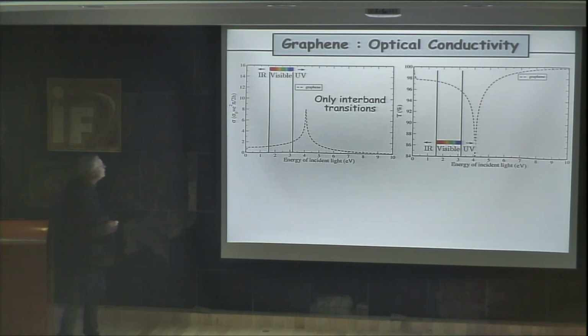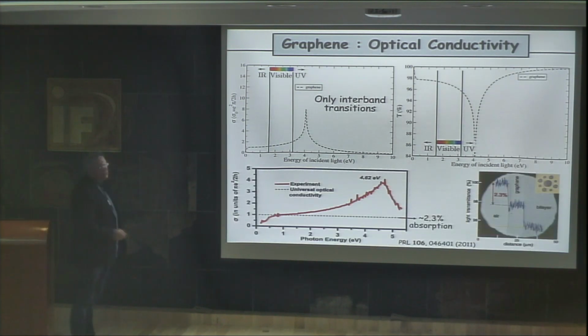So if we now want to calculate the optical conductivity, let's start with graphene to see if the model works. This is the curve that we obtained for the optical conductivity in graphene, and this is the corresponding transmission that is calculated. About 97.7% of the light is transmitted when it goes through a single plane like graphene, and this is what is experimentally measured. So we are in quite good agreement with what is measured experimentally. You have this plateau here, which comes mainly from interband transitions at the K point.